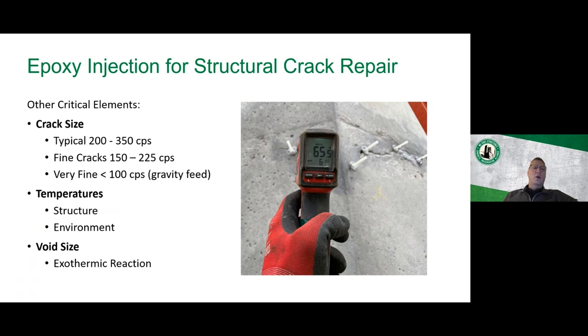And there are low temperature resins, epoxies, and there's also high temperature ones as well, because it's temperature sensitive. The higher the temperature, the faster the reaction. So if you're in a hot environment, if we're working in a paper mill and it's 130 degrees, if we're using something that's not made for high heat, that epoxy will set up too quickly and it'll gum up our machine or equipment, our injection heads, all of that. So we have to keep those in mind.